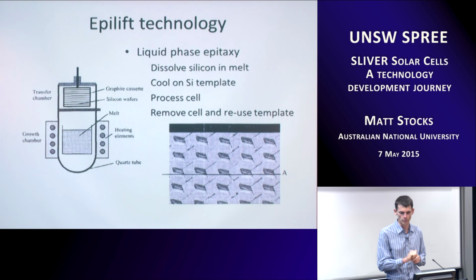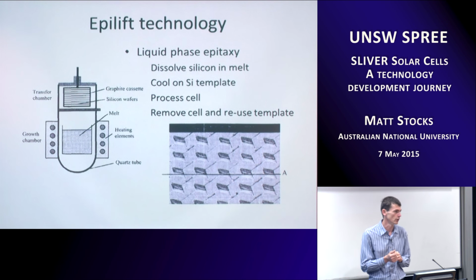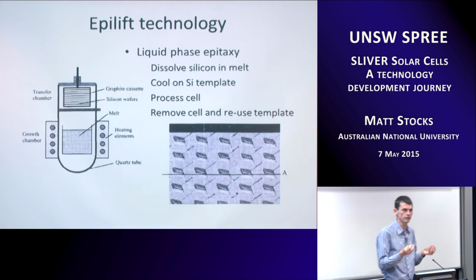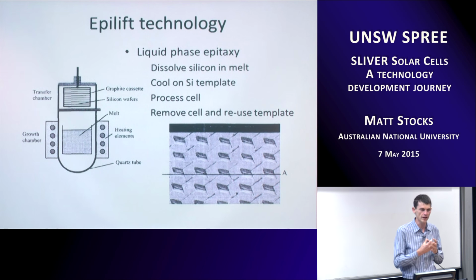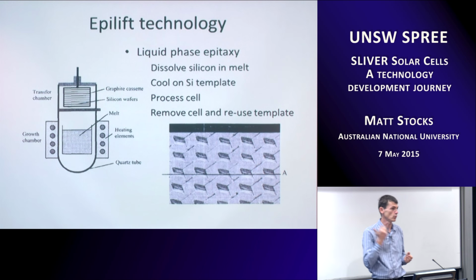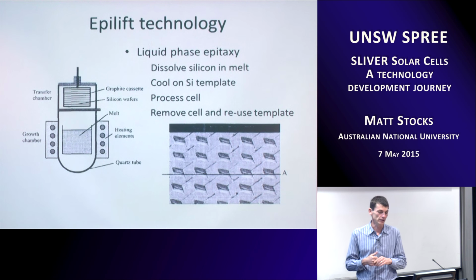And what you see down the bottom right is an example of a substrate that was grown, in this case a 111 silicon substrate. So what happens then is the silicon kind of wants to overgrow across the surface. So you can just have a few seed points on the surface, seed lines, and it can grow out and extend across the surface, have a few attachment points which are relatively weak, and we can just detach that layer.